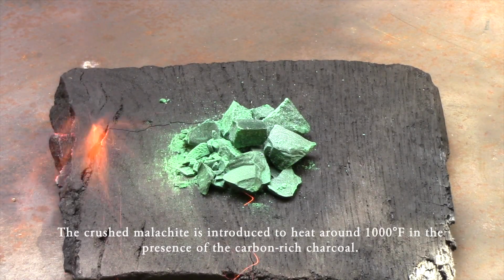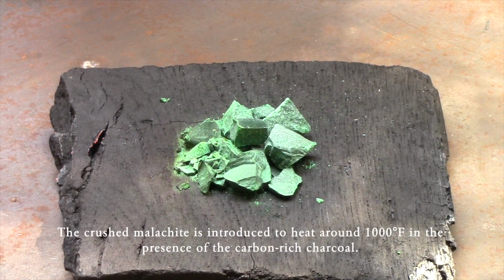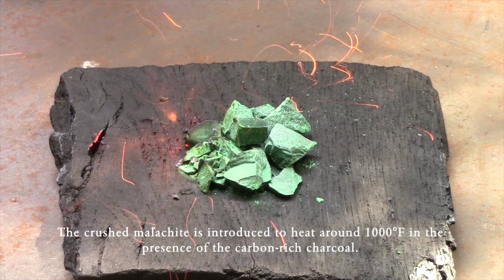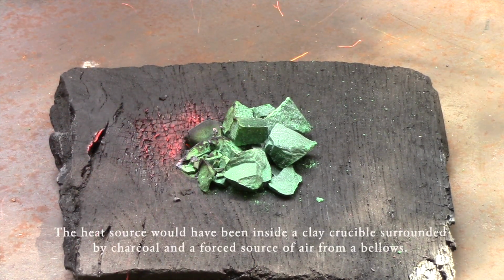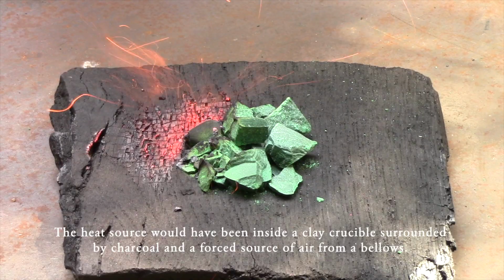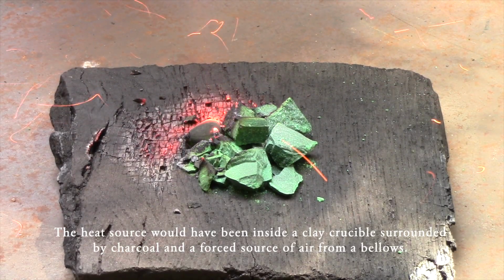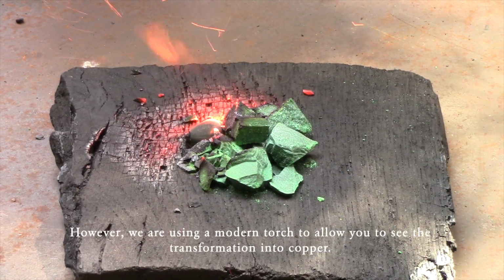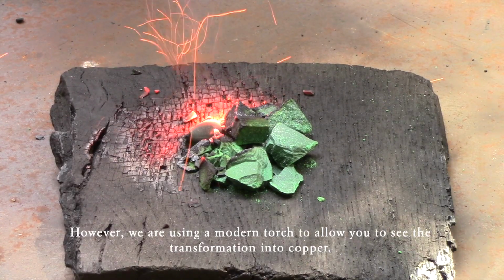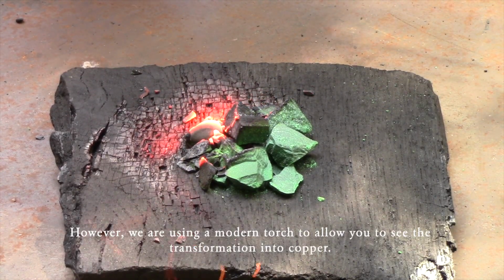The crushed malachite is introduced to heat around 1000 degrees Fahrenheit in the presence of the carbon-rich charcoal. The heat source would have been inside a clay crucible surrounded by charcoal and a forced source of air from a bellows. However, we are using a modern torch to allow you to see the transformation into copper.